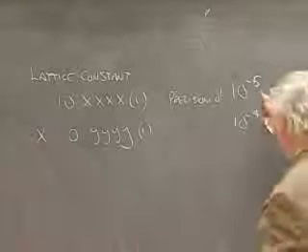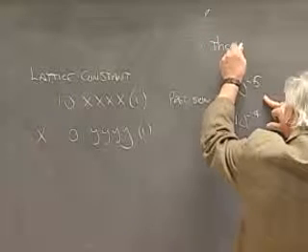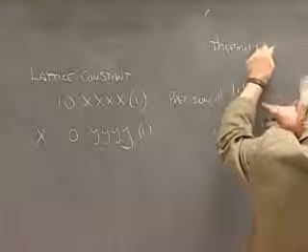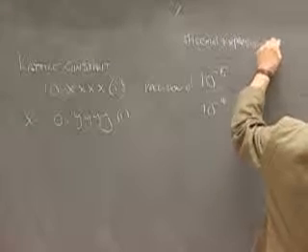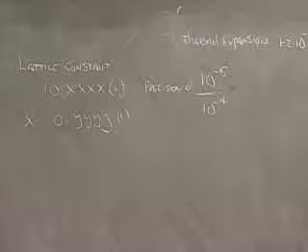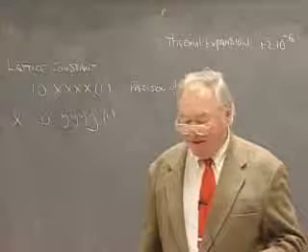One thing I always like to point out here is that the thermal expansion coefficient for most inorganic materials is something that never gets much lower than about 1 or 2 times 10 to the minus 6. So if you're going to push the measurement of a lattice constant to the ultimate accuracy, you better have a thermometer on the top of the X-ray generator, or your measurement is meaningless. The thermal expansion can be more than the uncertainty in your measurement. So you should report, for very precise measurements, the temperature at which you made your measurement.